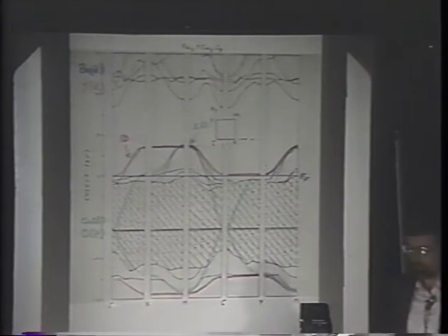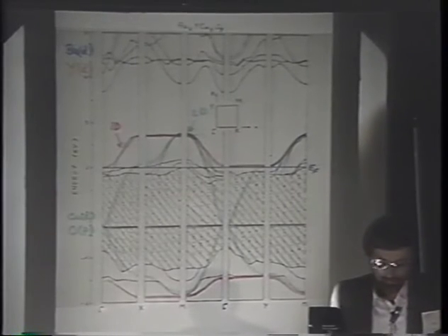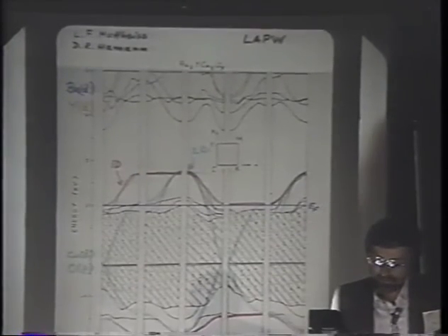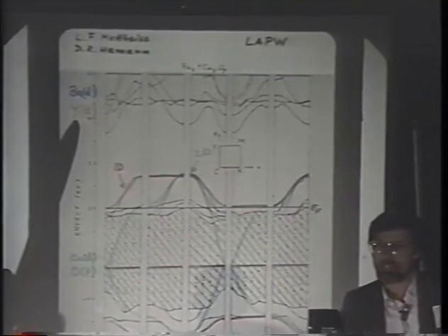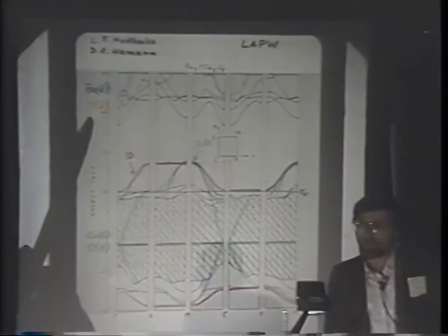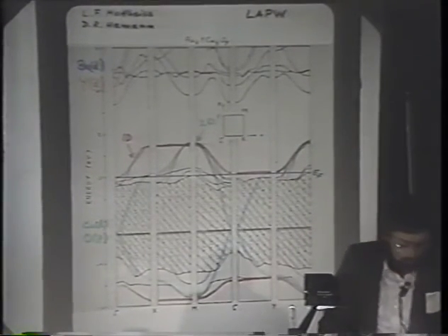On top of this now comes this one-dimensional chain, which gives these red bands. If the material is in the O7 form, then the Fermi level lies roughly in the midpoint of the two-dimensional band and at the lower end of the one-dimensional chain. I would also like to remark, and this you have seen before, that the barium and yttrium atoms indeed are only donor atoms. They are far away from the action near the Fermi level.